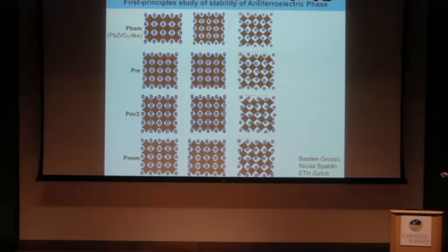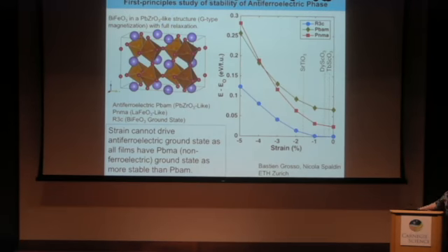So we know we have something with this pattern in the TEM, but it could be any of these phases, and they're still working to figure out what the lowest energy phase is and determine what's going on here and why we're driving this. But clearly we have these other non-R3C-like structures nearby in energy space, and just by coupling to the, making superlattices here, we've stabilized a new ground state. The other thing is this PbZrO3-like structure can't be stabilized with strain alone.